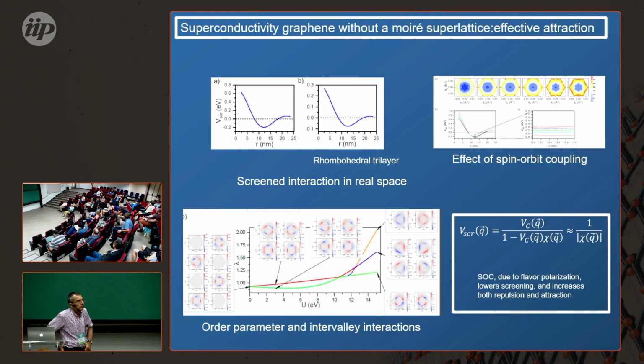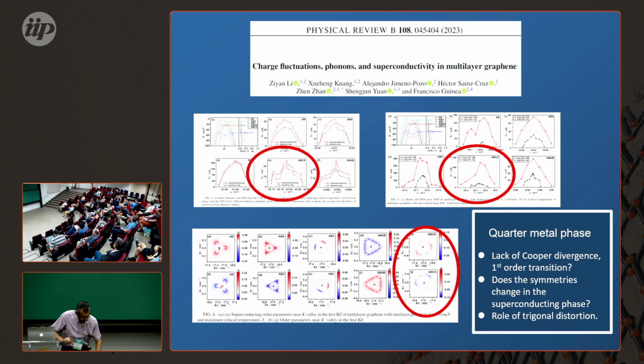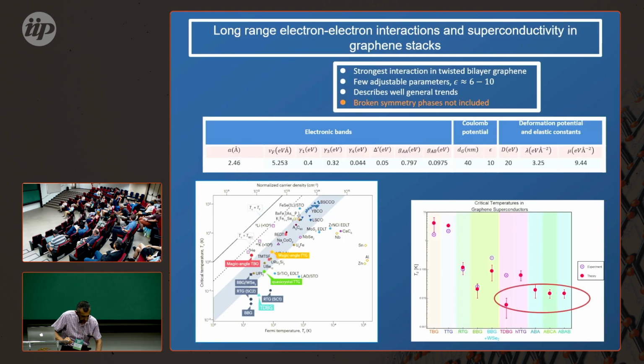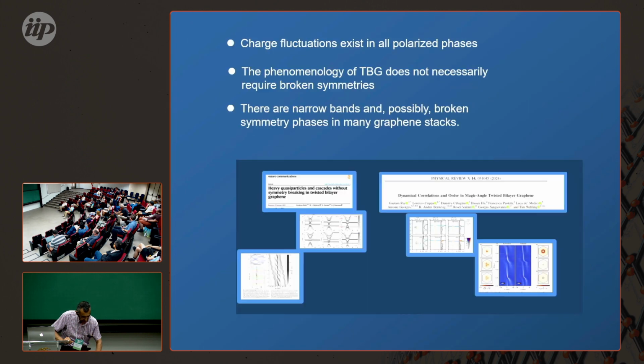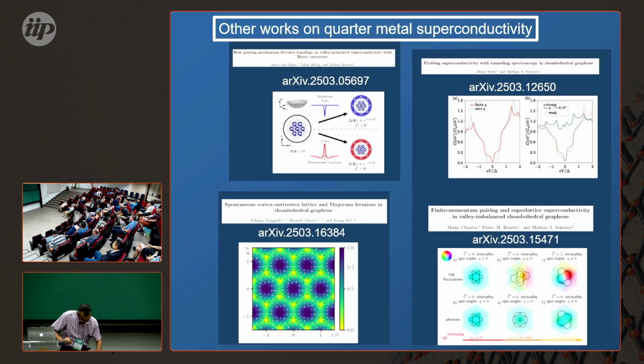So you went pretty fast on the quarter metal superconductor in rhombohedral tetralayer. Can you say what you expect the properties of this superconductivity to be? Okay, it's a mystery. Does it require a threshold of interaction? It's a mystery. If I tell you a little bit more of the history, we did our Hartree-Fock calculation, we looked for superconductivity, and we didn't find any superconductivity at all in the quarter metal. Then we realized that if you do a Hartree-Fock calculation, the density of states at the Fermi energy is by definition 0. It decays logarithmically to 0. It was well known already in the 80s, because it's due to the long range.